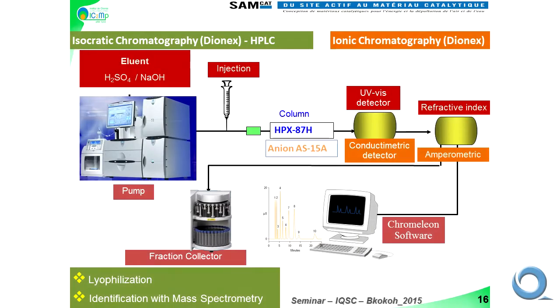It depends on the co-catalyst at the surface of palladium. So I show you the system we have. We have two chromatographies. Isocratic one, Dionex HPLC, where you use sulfuric acid as eluent. And automatically, you have a system to inject the solution.